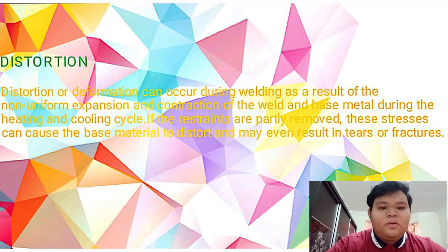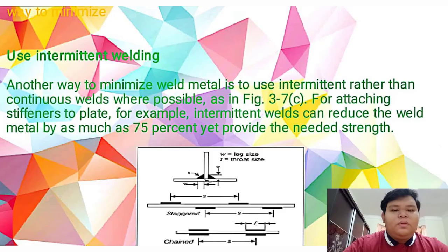Distortion or deformation can occur during welding as a result of the non-uniform expansion and contraction of the weld and base metal during the heating and cooling cycle. If the restraints are partly removed, these stresses can cause the base material to distort and may even result in tear or fracture. The way to minimize: use intermittent welding. Another way to minimize weld metal is to use intermittent rather than continuous weld where possible, as in figure 3.7c.